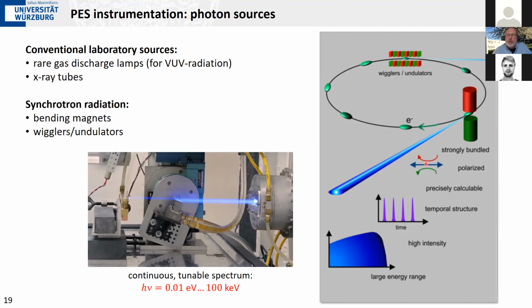The light coming out of the ring is polarized, so you can use also the polarization to do certain experiments. It can be linearly polarized, but it can also be circularly polarized. That's, for example, important if you want to do XMCD, X-ray magnetic circular dichroism. And the light coming out is structured in time, because you don't have a continuous electron beam here in your storage ring, but you have a sequence of electron bunches, electron packets that run around here that are equally spaced in distance, and so you get a certain time structure in your beam, and that you can use also for time-dependent experiments. So it's a very versatile, very intense light source, but of course it's also a complex light source.